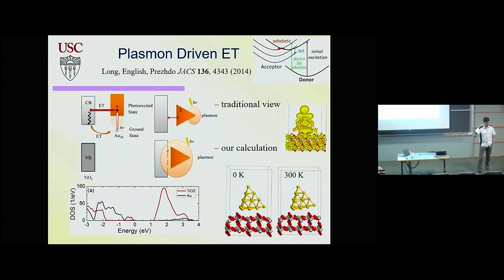Another question is now charge transport between a semiconducting and a metallic particle. The traditional picture is that you excite a plasmon, and then the plasmon breaks into electron-hole pairs, and then the electron would transfer to a semiconductor, for example. And the question I've always had is, how come they don't just relax vibrationally? Metallic particles are pretty large in experiments, they don't have any energy gap, everything should go to heat very fast.